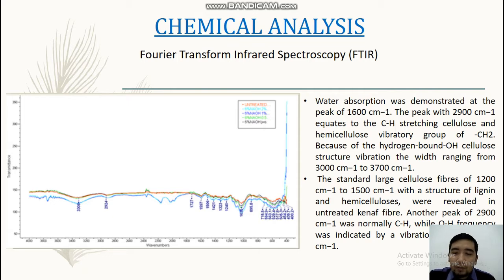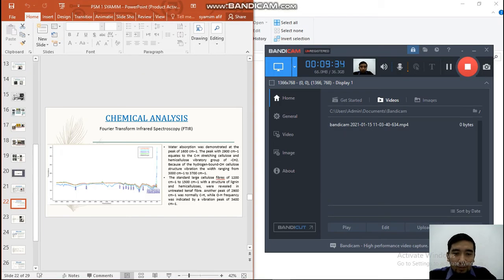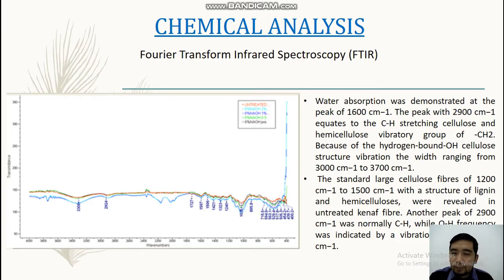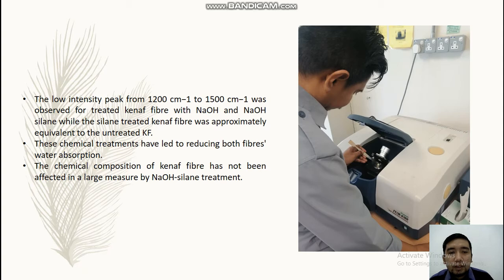Another peak of 2,900 was normal CH with OH bond was indicated by vibration. Okay. For vibration peak is 3,400. Okay. The low intensity peak from 1,200 to 1,500 was observed for treated Kenaf fiber with NaOH and NaOH silane, while the silane treated Kenaf fiber was approximately equal to the untreated Kenaf fiber. This chemical treatment has led to reducing fiber water absorption.